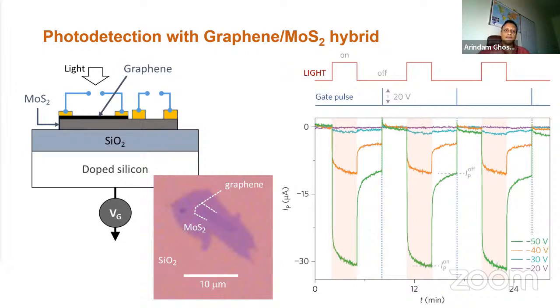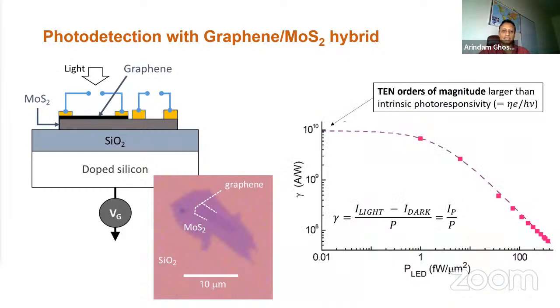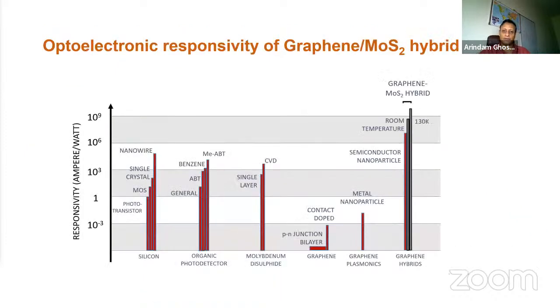And a figure of merit in any optoelectronic element is how much photocurrent you get for a given power of light. And it turns out that this number, called photoresponsivity, is nearly 10 to the power of 10, which is 10 orders of magnitude larger than the conventional intrinsic photoresponse in bulk semiconductors like silicon, germanium, and semiconductors like that. So this essentially led to a very interesting new set of devices. If you compare the graphene molybdenum disulfide hybrids to standard silicon detectors, the responsivity is nearly 10 orders of magnitude larger. You can see this is about 1 ampere per watt.